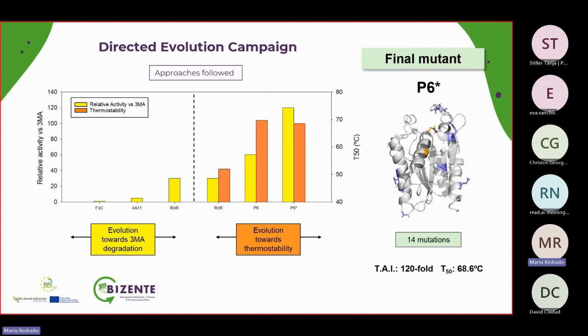The directed evolution campaign followed two approaches. The first one, on the left, was based on improving the hydrolysis of the model molecule. And the one on the right concentrated the efforts on finding thermal stability, which is one of the key points for enzymatic biodegradation. And finally, after a lot of effort, they all converge in this P6 that I just mentioned before. That's the final mutant after 14 different mutations, and as I already mentioned, with a great activity and very good thermal stability.